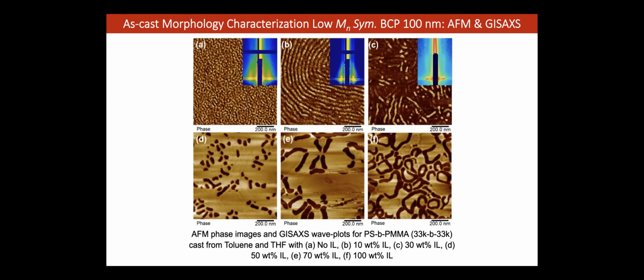So here you can see that in fact, this is now a symmetric, lamellae forming symmetric block copolymer system. And you can see that B probably is the best. And indeed AFM shows you this fingerprint pattern. So you add 10% ionic liquid, it is getting you the best results. And if you add too much, you are changing the structure to the point that it is no longer internally vertical as it shows on the surface. So surface and internal structure are fairly well correlated, but you can't assume that from the get-go. And you really need to do these measurements.